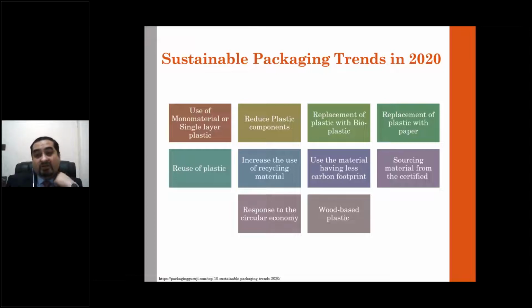With regards to bioplastic, you do need to realize that they have a huge problem with regards to their price. Okay, their price is too high, even up to now. In Pakistan, the minimum that you can get is 800 to 900, and even those materials don't have the desired quality. Good quality biopolymers, PLA, PBAT, PBS, start at 1200 or even higher prices per kg. Prices are there in the market. So bioplastics, although a good option, at the moment can't directly replace the multi-layer structures.